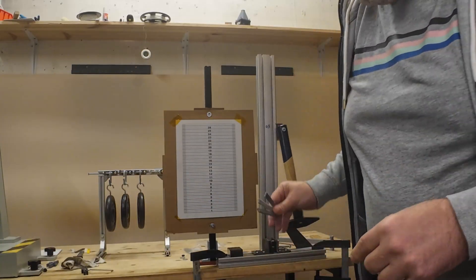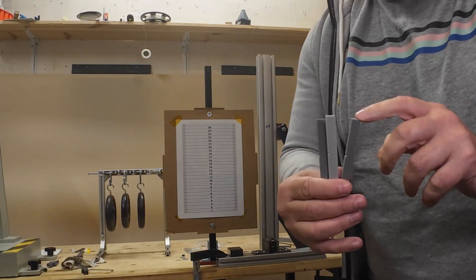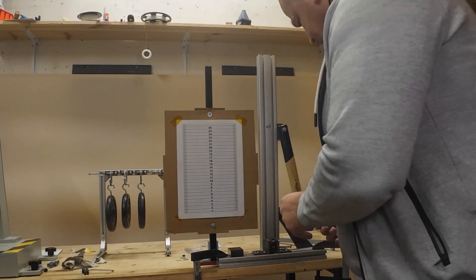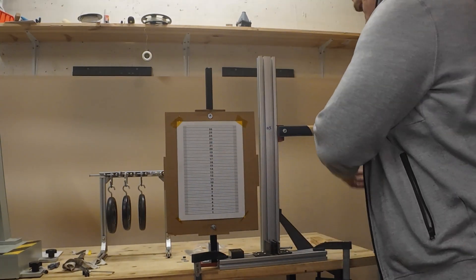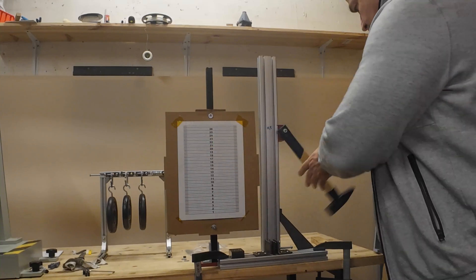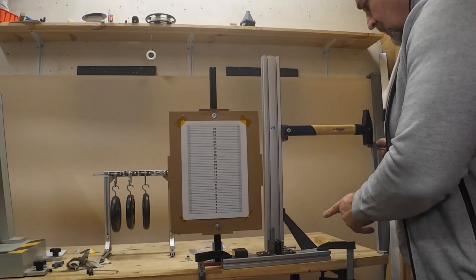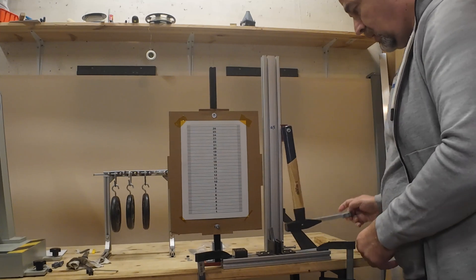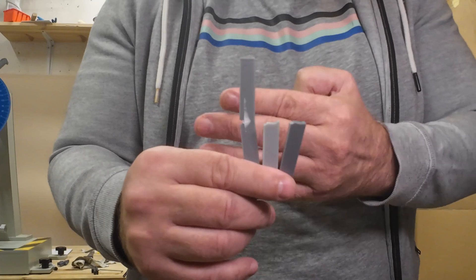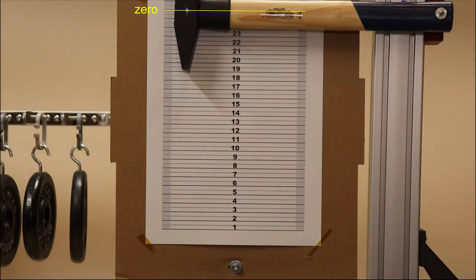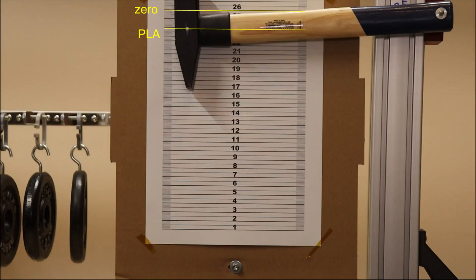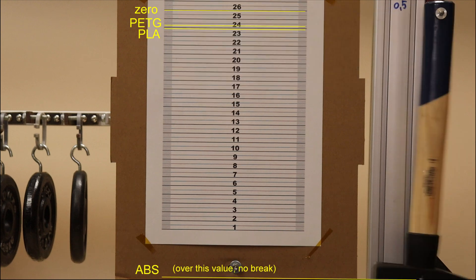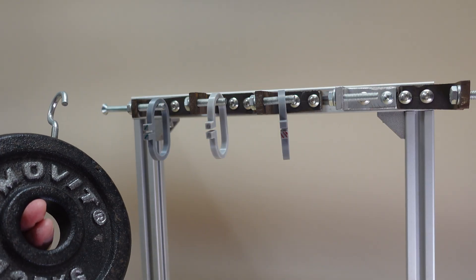The Izod impact test with this 1.5kg hammer—here the ABS should dominate. PLA at zero position, PETG, ABS. Only three times it happened that the object didn't break under this 1.5kg hammer. This is zero position, this is after breaking the PLA, and this after breaking the PETG. This means the PETG is slightly more brittle material compared to the PLA, and this is the ABS. The breaking energy is much higher because the object did not break.